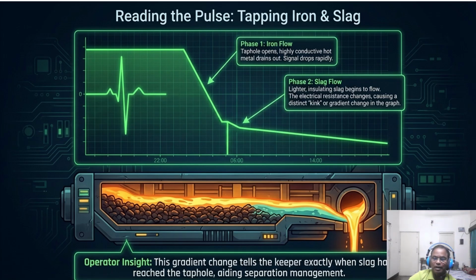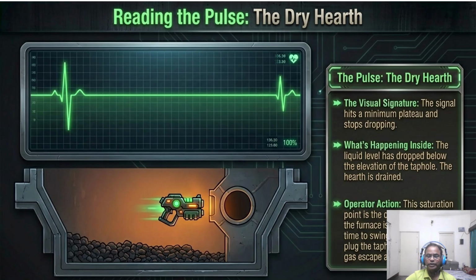Eventually this signal will level off, which brings us to the most critical decision point. Now this is the pulse, the dry hearth, where the signal hits a minimum plateau and stops dropping. This is saturation. This saturation point is the definitive signal that the liquid level has already been drained, as is shown here. So this is the optimum time to swing the mud gun and plug the tap hole. It prevents the hot gases from escaping and reduces unnecessary wear on the tap hole refractory, which is very detrimental for the furnace campaign.